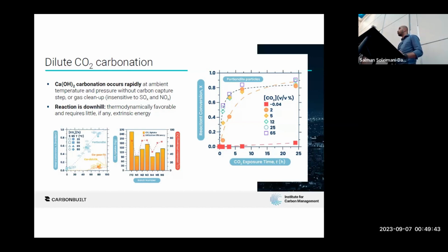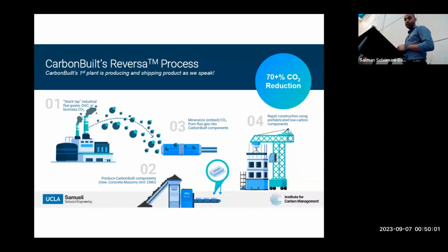This is really quite important because at that point, we were really focused on flue gas. We were looking at, what is the lowest concentration of flue gas you could use. As an example, a natural gas power plant puts out CO2 at about 3%. We saw that there was a really good opportunity here, right? So we ended up going out to build this particular idea into a company. And where this all went is it ended up with CarbonBuilt, right? So CarbonBuilt is taking essentially concrete block and carbonating concrete block, doing it all at ambient pressure, ambient temperature, using dilute CO2. And it gives you a significant CO2 reduction because you've got lots of utilization happening. And in fact, their first commercial plant went into production and is essentially producing and shipping block as we speak.